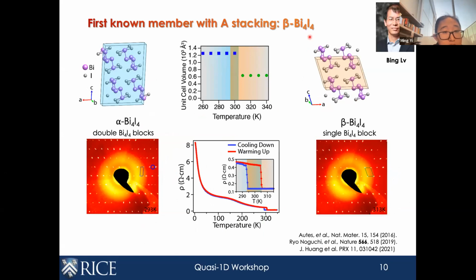So in actual crystals, the first known member with the simple A stacking is the beta phase of bismuth iodine. This has already been studied by a number of groups, but this is our measurement with our collaborator Bing Lv's group. Here, from single crystal X-ray diffraction, they can see that there's a natural lattice distortion around 300 Kelvin, at room temperature, above which the crystal shows a unit cell of a single layer. And this is the beta phase. This is the simplest stacking order. And then when you go below this transition, which is a first order transition shown with the hysteretic behavior, there are additional diffraction spots, which indicates that now the unit cell has doubled. And this is the alpha phase. I'm going to come back and talk about this later.